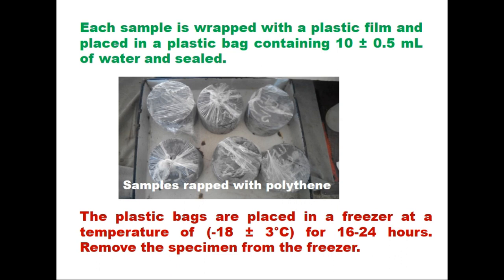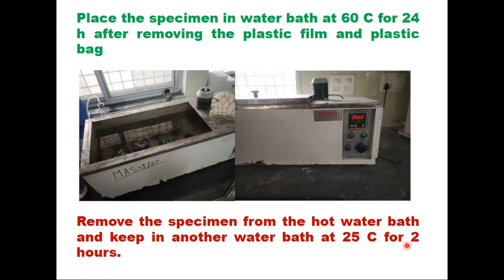The plastic bags are placed in a freezer at minus 18 degrees centigrade for 16 to 24 hours. After removing the specimens from the freezer, remove the plastic film and plastic bag and place the specimens in a water bath at 60 degrees centigrade for 24 hours. Then remove the specimens from the hot water bath and keep them in another water bath at 25 degrees centigrade for 2 hours so that the specimen temperature reaches the test temperature.